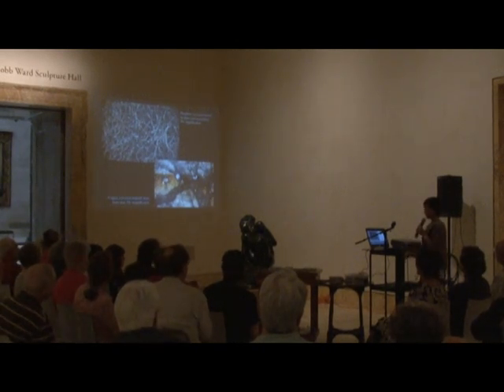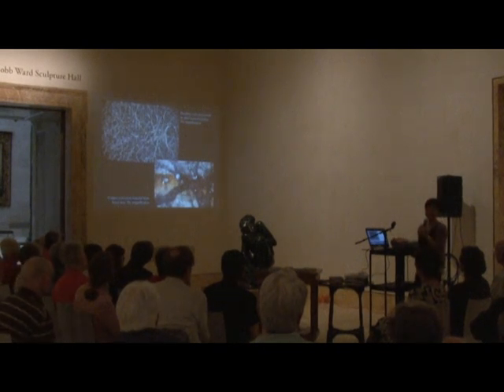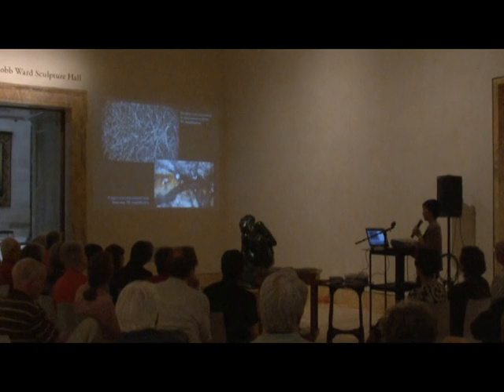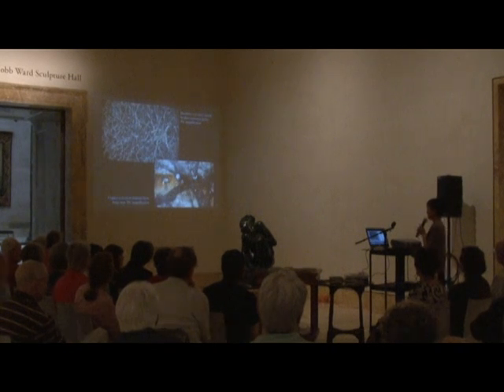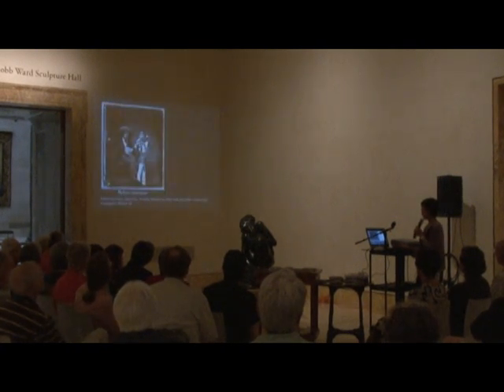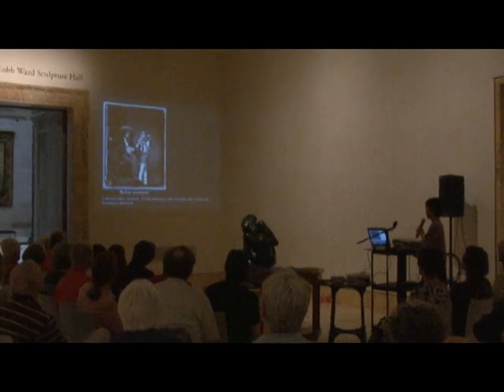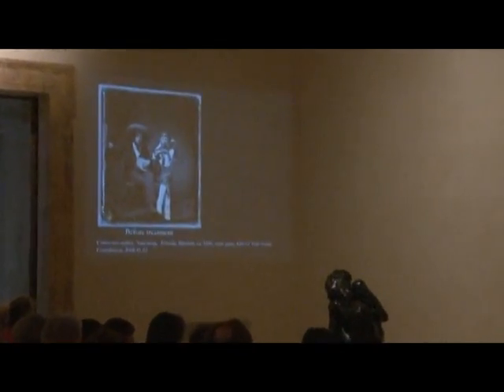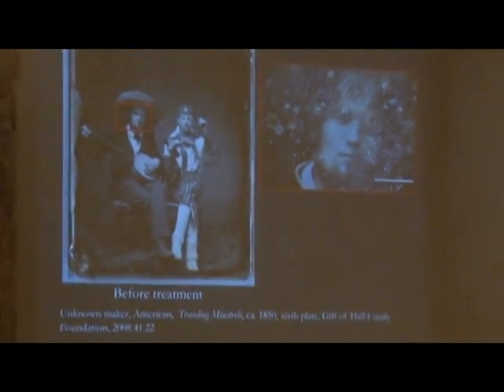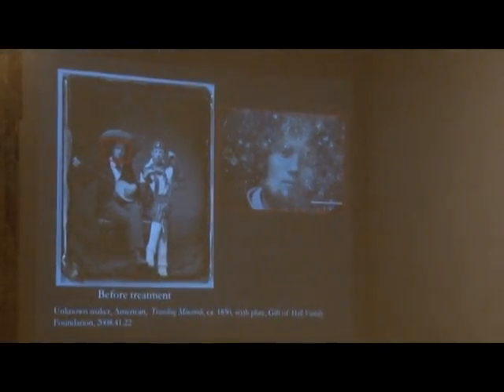So our best approach is to keep these conditions from happening by means of providing a good storage environment and good housekeeping. But once the corrosion is at this stage, intervention becomes necessary to keep this condition from advancing. Some of the pieces in the exhibition had already reached the point where corrosion is so prominent that it is distracting to the viewing of the image. This plate had corrosion spots scattered all over the top half of the image. And when corrosion is this advanced, liquid immersion treatment becomes necessary, since the surface is too fragile to take any kind of mechanical manipulation.